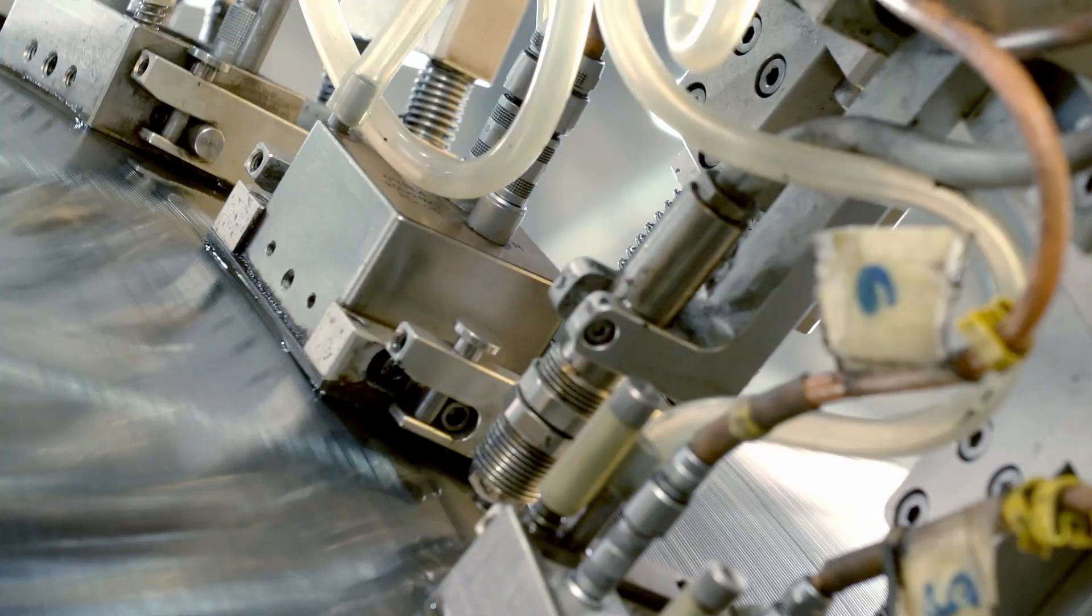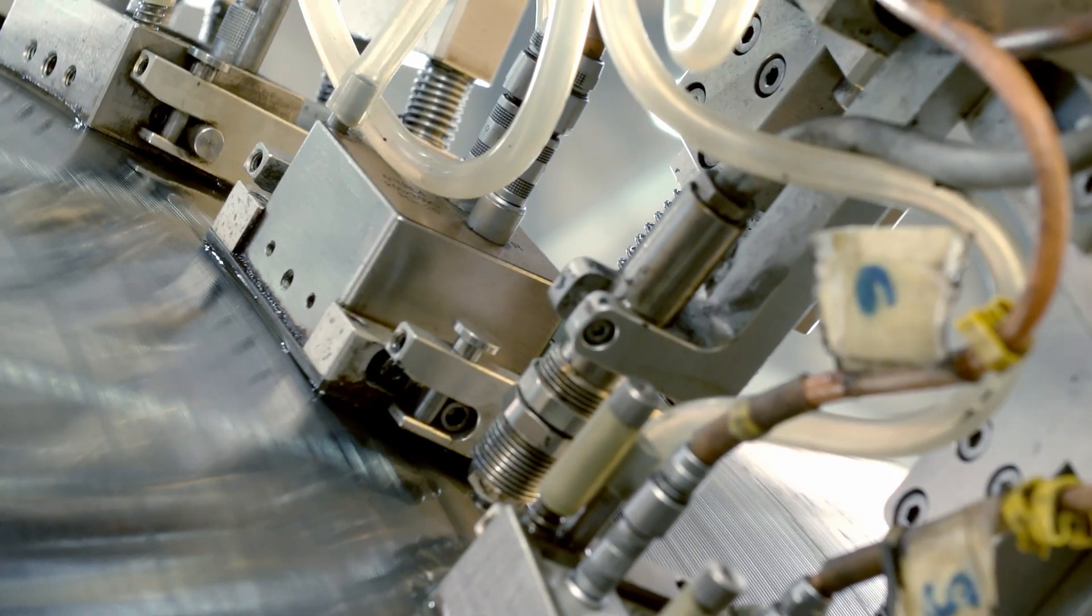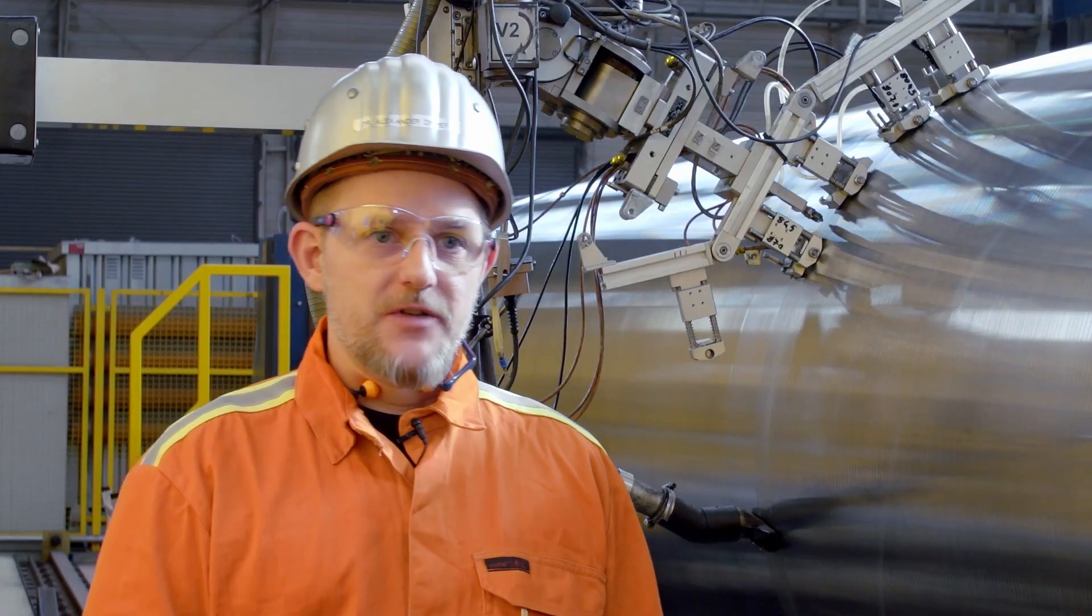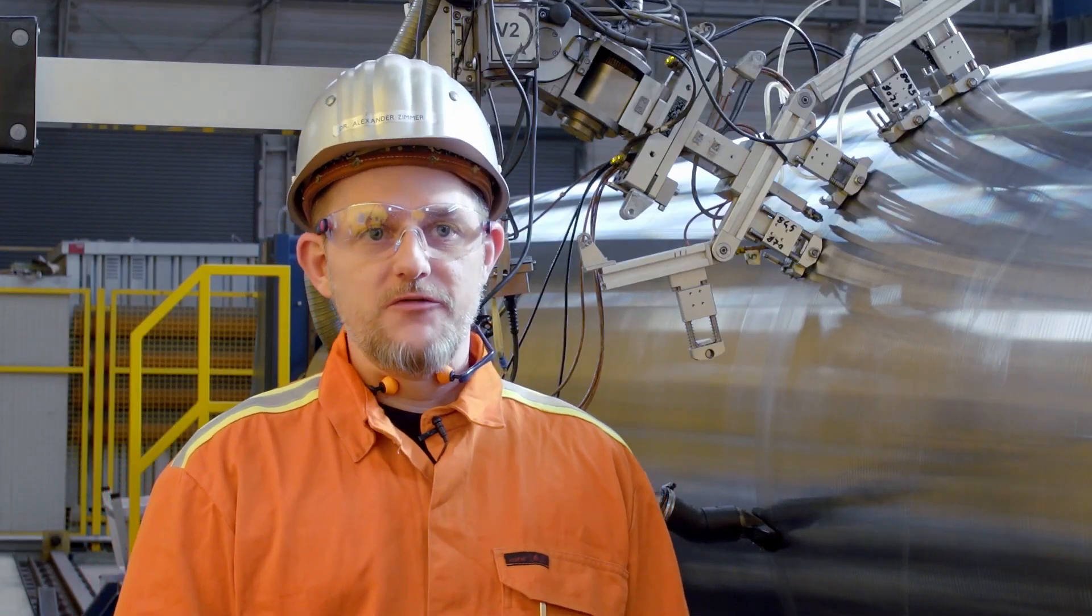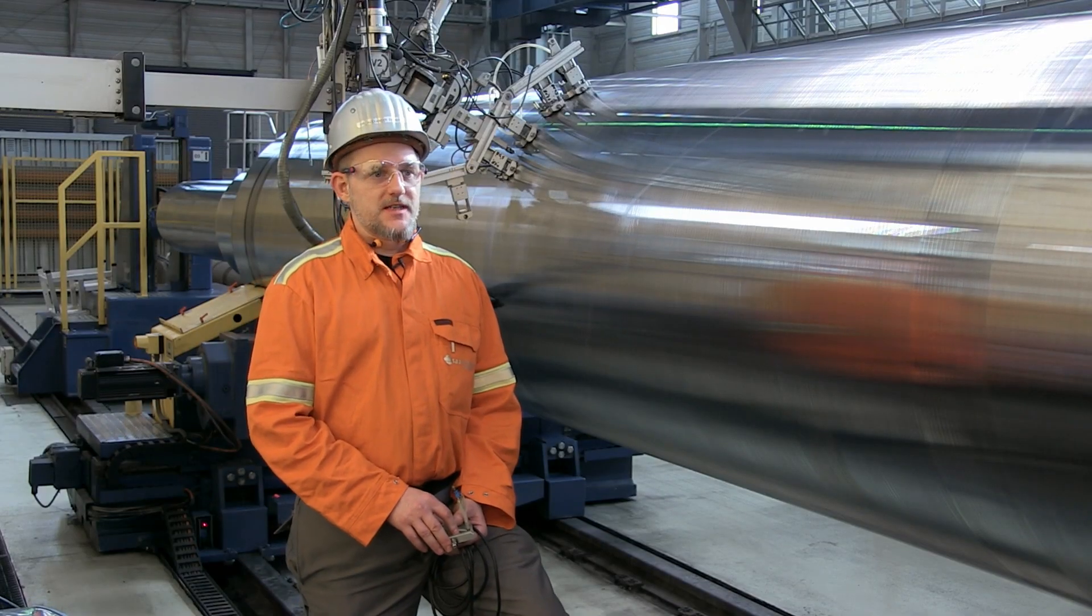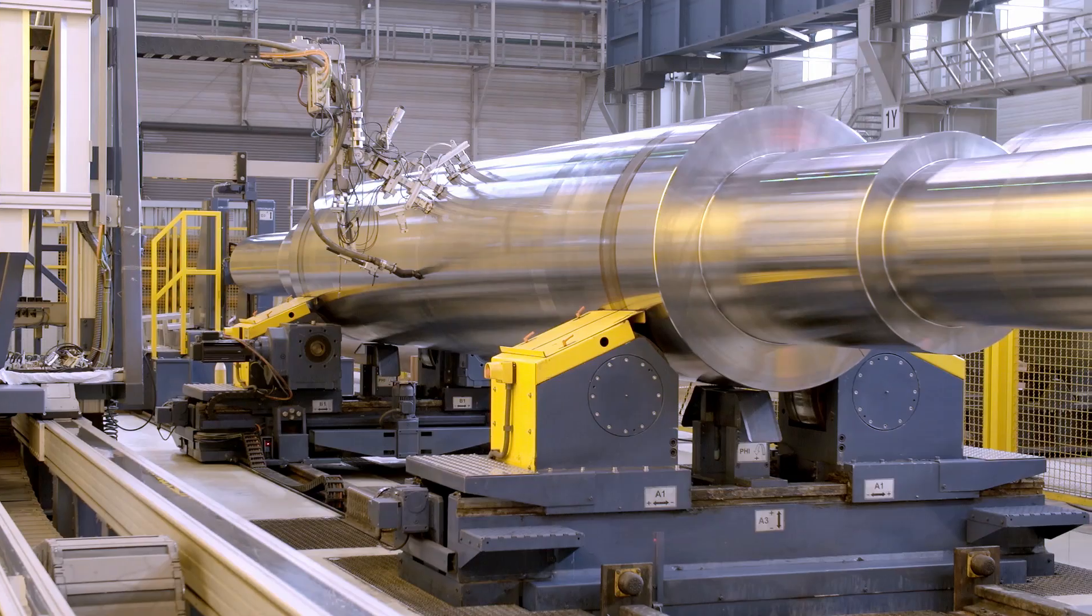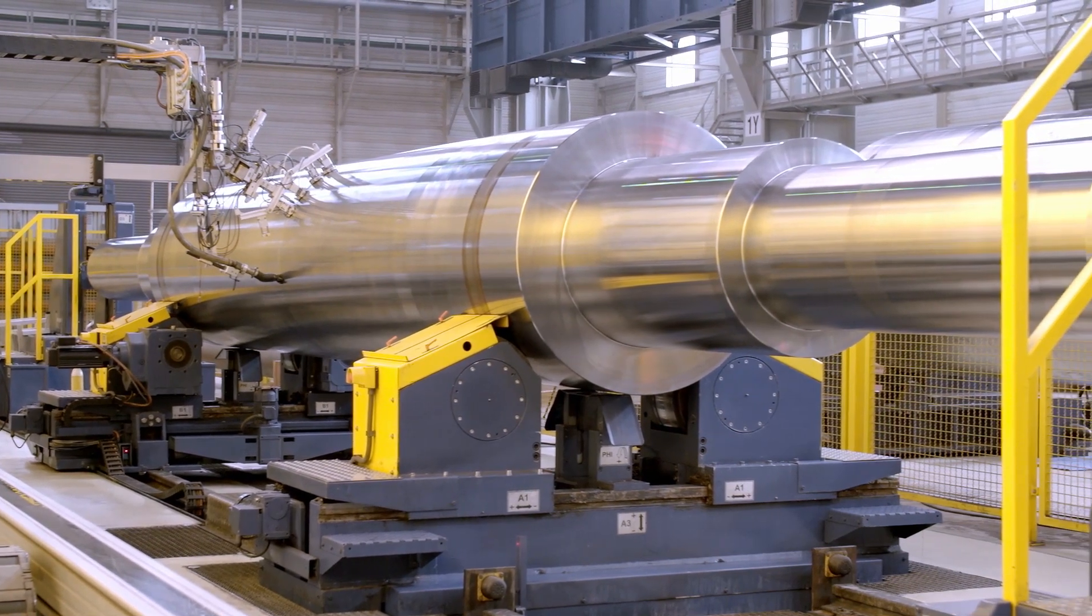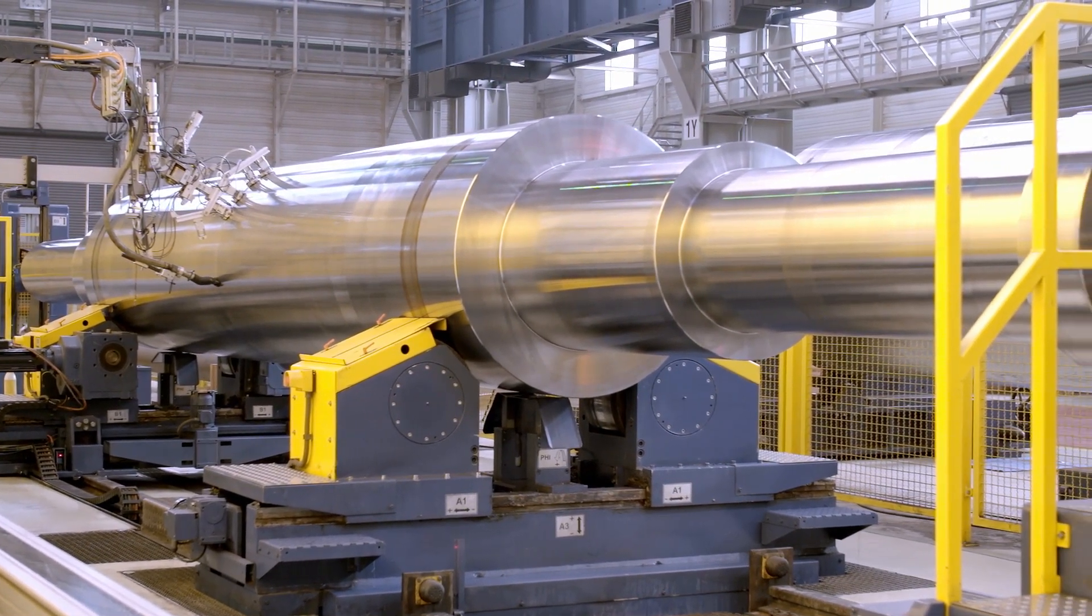The testing head is placed on the workpiece, connected to it via a thin film of water, and transmits ultrasonic sound into the workpiece. This ultrasonic sound is reflected in the workpiece and received back by the testing head before being logged on a computer where it can be evaluated. A long shaft like this one may involve up to four days of testing.